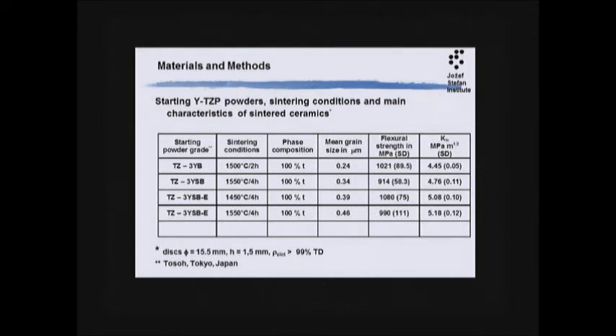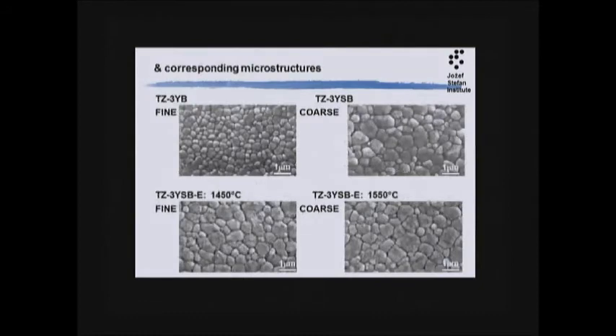So you'll see that the finer grained materials generally, so B and BE, will typically have higher strength than SBE with a bigger grain size, same here, but lower fracture toughness. So the material that has finer grains will have a higher inherent strength but lower fracture toughness. And to give you an impression of the grain sizes.